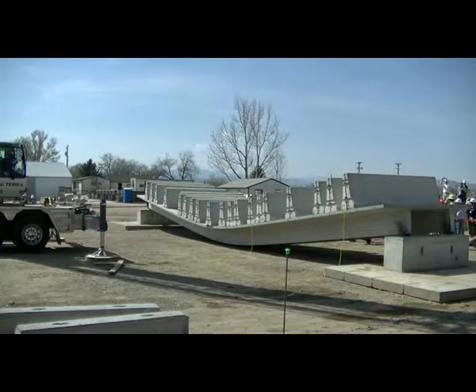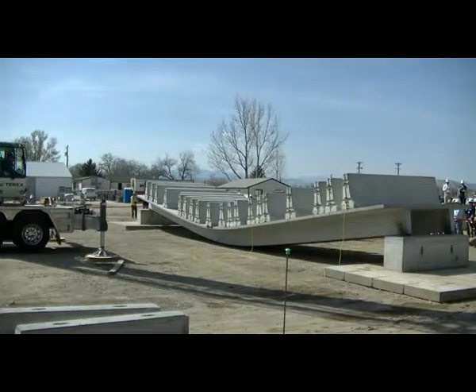Flexural cracks were present as expected, but there were no signs of duress. The continued application of blocks now clearly begins to show the ductility of pre-stressed concrete and the warning signs of an overloaded structure. Blocks were added until near failure at 20 blocks or 88,000 pounds. At that point, the total flexing of the bridge was 48 inches, nearly 3 times the prescribed service load.